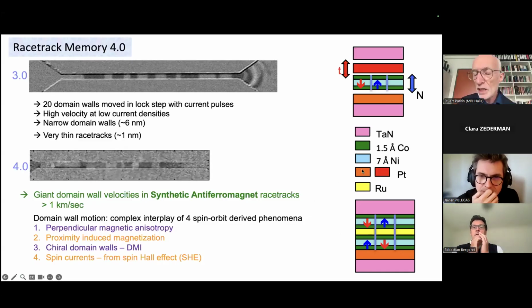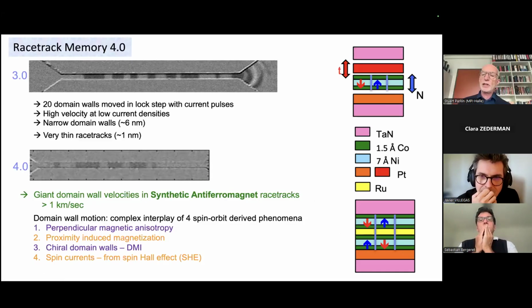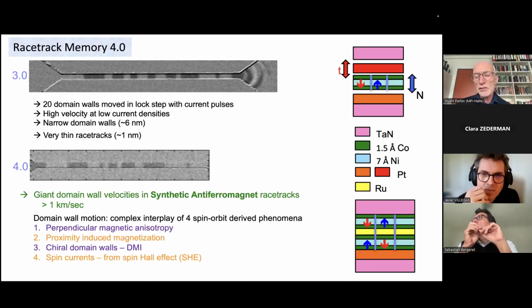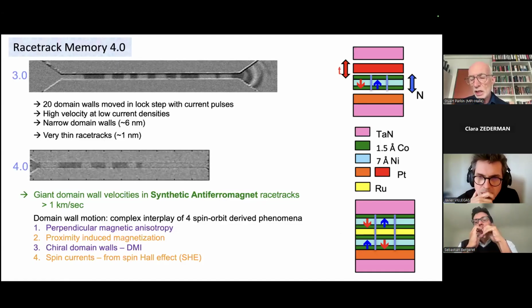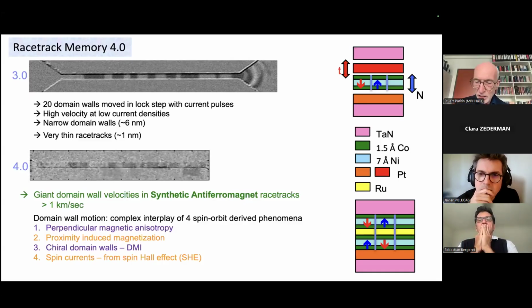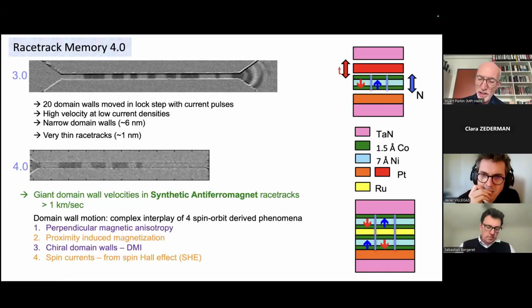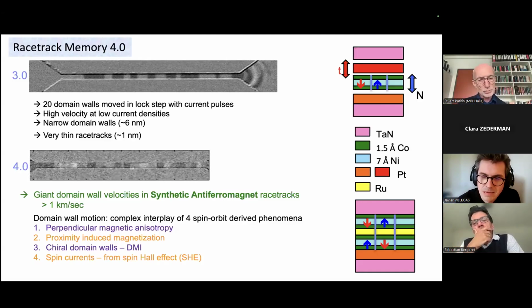And ruthenium is something I showed a long time ago, in 1990, 1991, gives rise to a huge oscillatory interlayer coupling depending upon its thickness, and for very thin ruthenium, the magnetic coupling through a so-called Ruderman-Kittel interaction is antiferromagnetic. In fact, it's very, very large. It's about 1% of the exchange within the magnetic layers themselves. So this system gives rise to these very large velocities of domain walls.